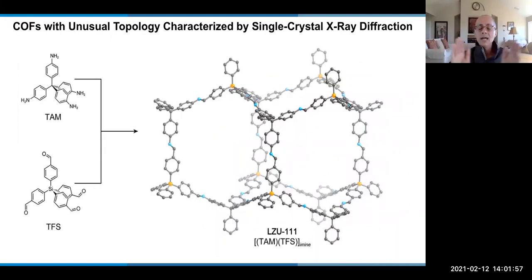Also, you could make COF structures that are not the most symmetric possibilities, and so they were not easy to guess. They're really very hard to guess that they're going to form. And without single crystal X-ray diffraction, it would be very difficult to refine them from powder, as illustrated here in this hexagonal diamond type structure.